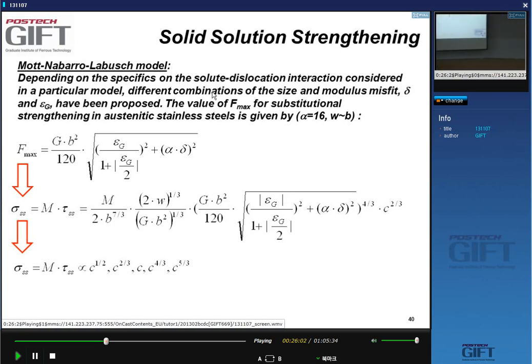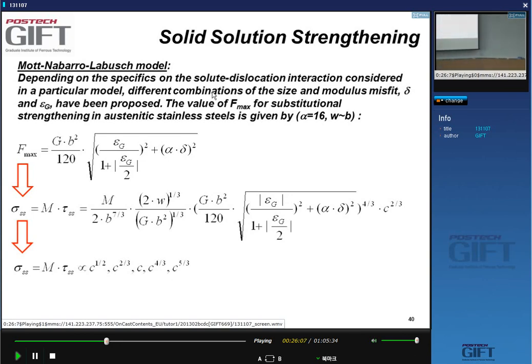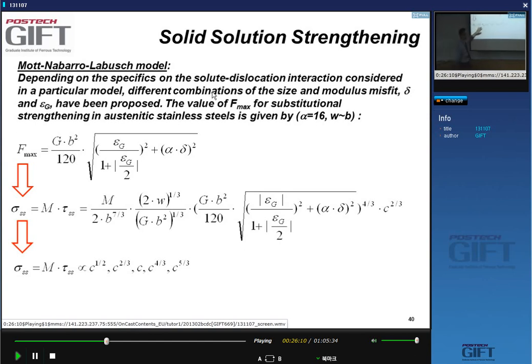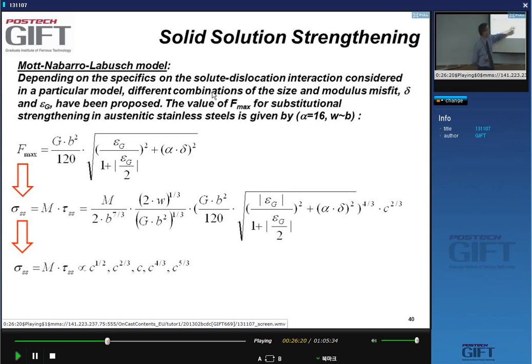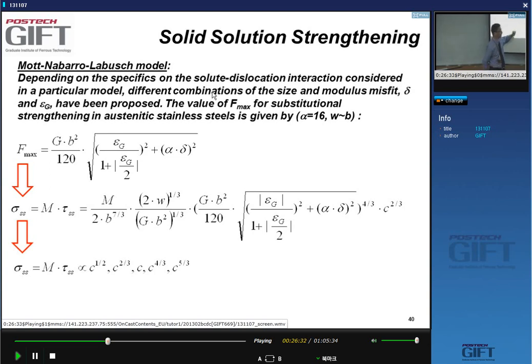You might think we can easily test this by measuring strengthening as a function of concentration, but it doesn't work in practice. The amount of alloying we can do is always very limited. For instance, with silicon, you cannot add it indefinitely — very quickly you get an ordered structure with properties very different from a simple random solid solution. Combined with experimental difficulties in getting pure binary alloys, there are many cases where we still don't know which theory is better.